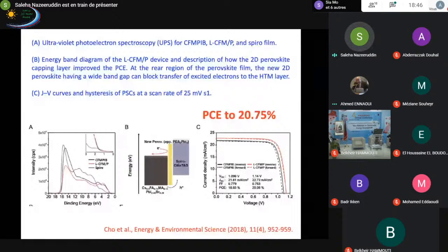So what happens when you shine the light on the perovskite? You create charges within this perovskite. The electrons, they turn around. They will not be able to tunnel towards the hole transporting materials, going towards and being extracted into the ETL layer. Whereas positive charges from the three-dimensional perovskite tunnel through the two-dimensional perovskite to the hole transporting material.